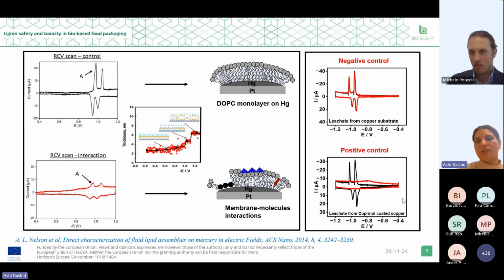Whereas in the bottom RCV plot, we can see that both of the peaks are expressed completely. So here we can see that the leachate obtained from the cuprinol coated copper substrate has completely damaged the membrane. Cuprinol, we know, is a wood paint, fungicidal paint, and we know it's toxic. So that's why we have used this as a positive control.